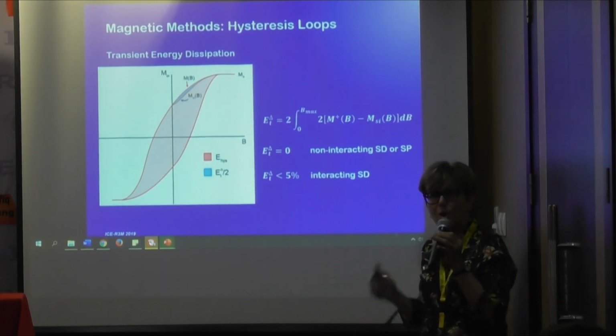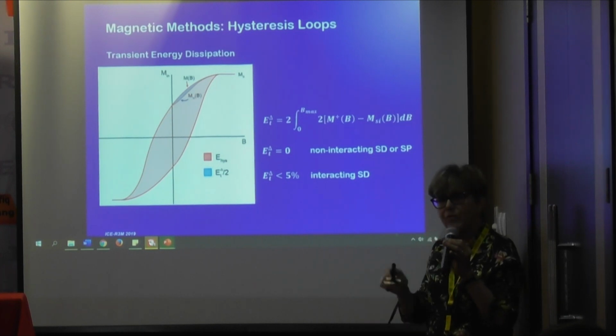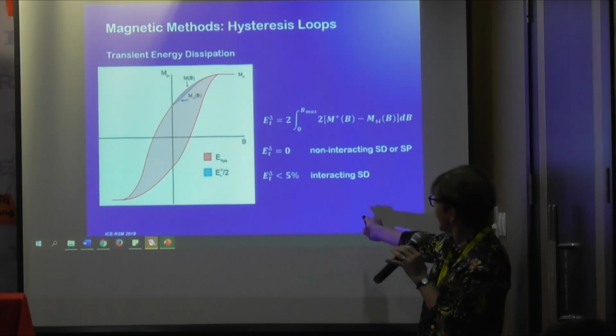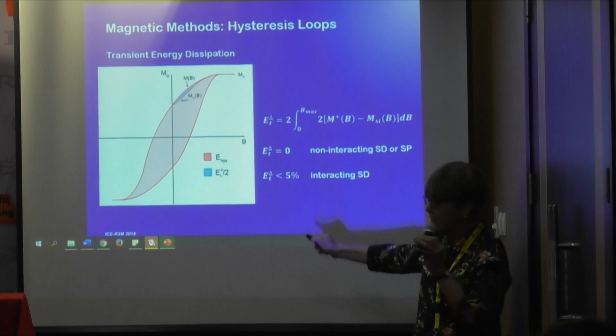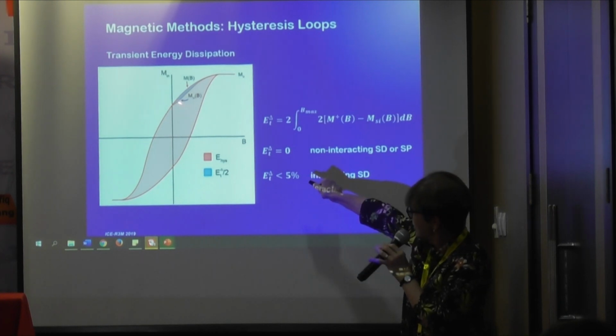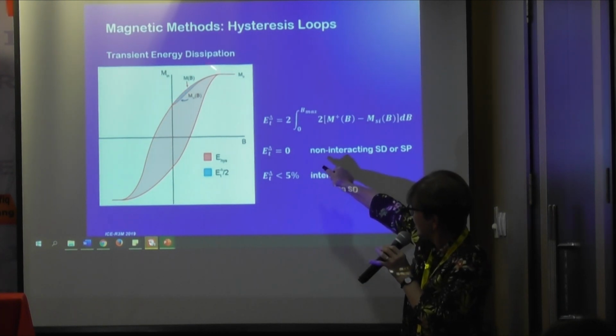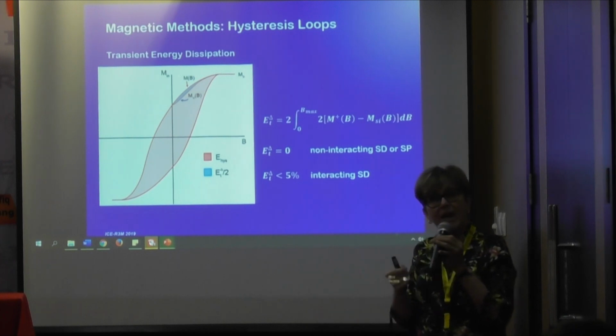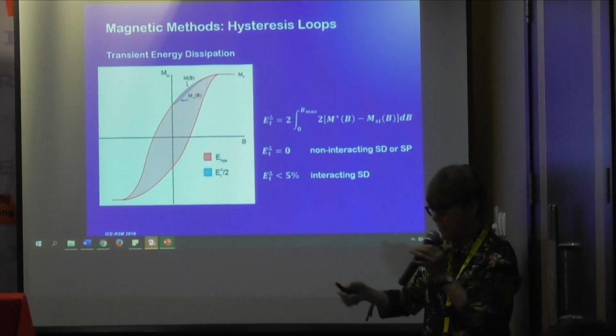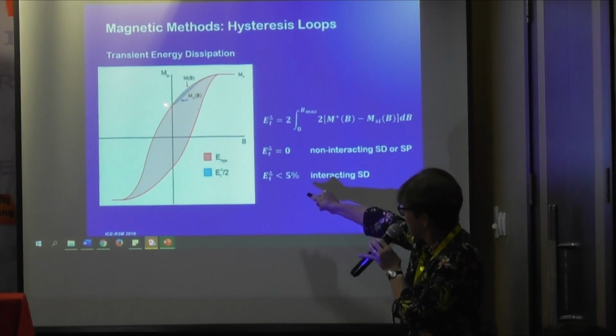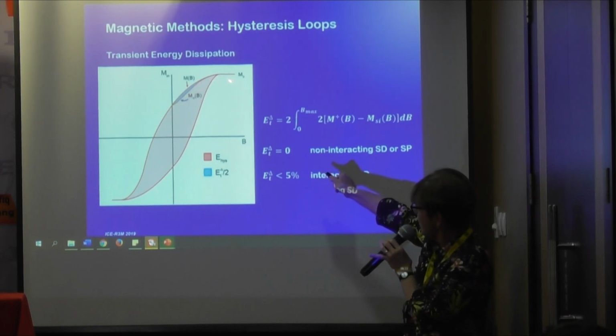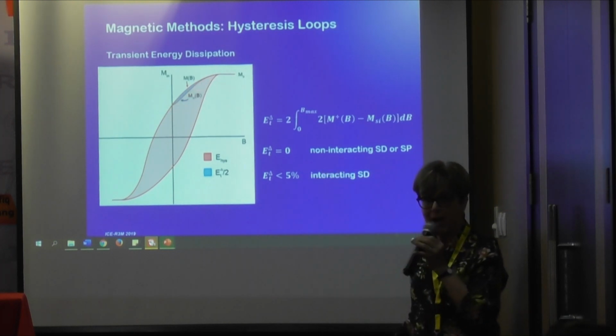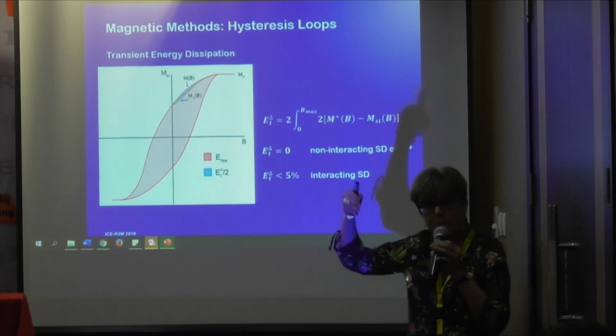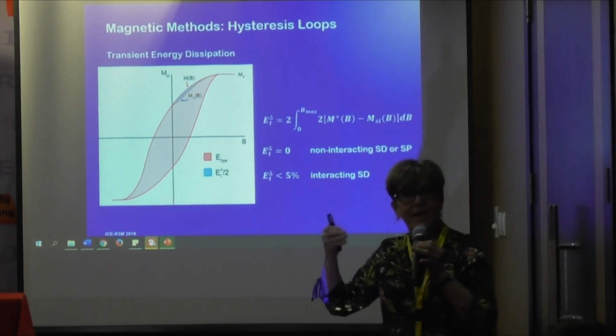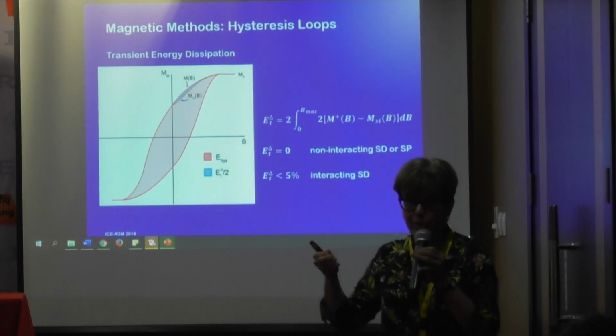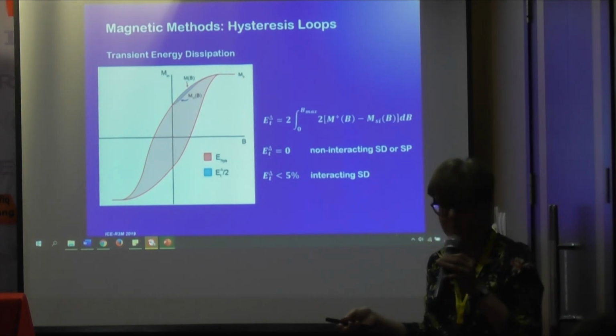Now, if I have a perfect single domain grain with no interaction, or if I have superparamagnetic, then my curve will start here and it'll trace up here and come back. But if I have interaction between my particles, then I will usually come up on a lower path here, and when I come back, it'll be on a higher path. And the area between those two curves can give me an indication of how much interaction I have between my particles.